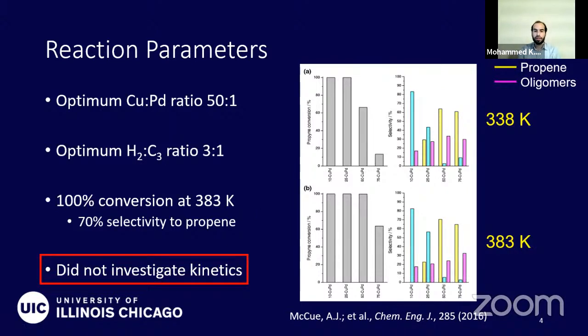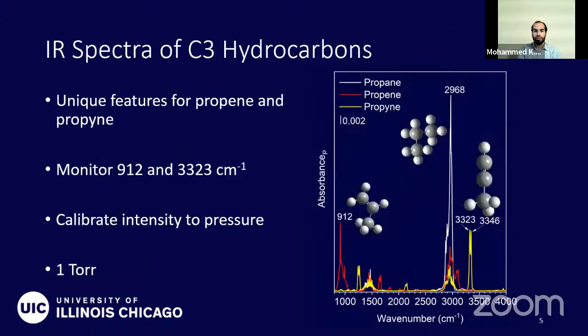So using infrared spectroscopy, because it's non-destructive, we can identify the infrared spectrum of each molecule, and focus on specific peaks such as 912 wavenumber for the CH2 bending mode of propylene, or the 3323 wavenumber for the CH stretching mode of propyne. And so we can monitor these peak intensities in real time and use that to determine the rate kinetics, the rate constant, the kinetic order, and the activation energy for the overall reaction.